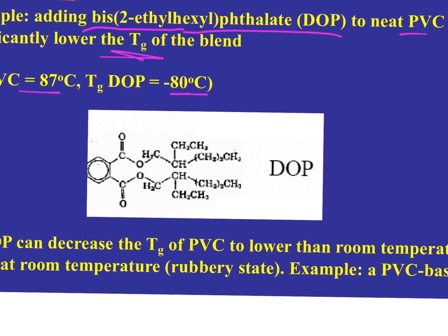And note that we've got a couple of different things going on here. We've got that polarity there, and so we need that polarity to go and mingle with PVC. All right, so this is actually very important, this engineered structure. And then outside of that, we have all this non-polar structure, all right? And so that helps make space, and allows this basically to swim around inside the PVC chains and keep them apart.